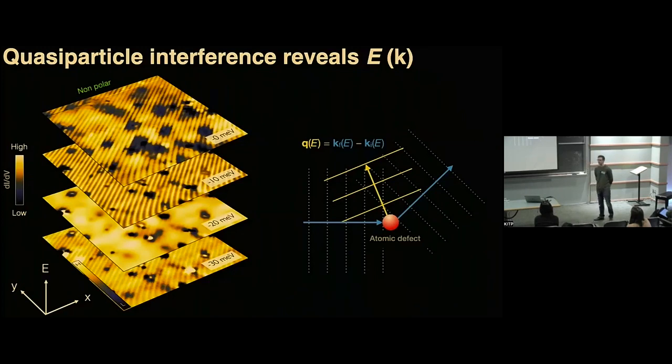That's proportional to the density of states, and we can measure this with angstrom-scale spatial resolution and millivolt energy resolution. A map like this will take 3 to 4 days to record. Everything has to stay exactly still while it does. But when you come back, it contains an enormous amount of information about the wave functions in the system.